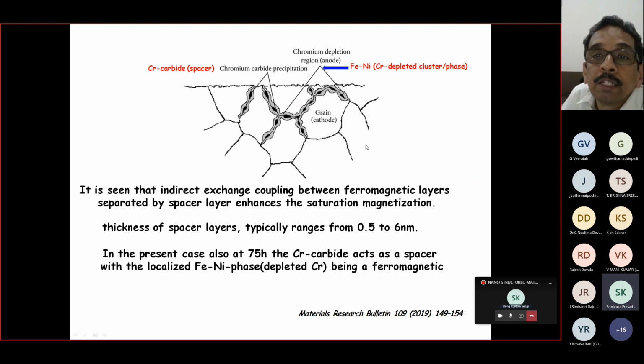And why this anomalous behavior? We try to explain it by saying that this is the chromium carbide precipitation, which I put in the dark region, and this is the iron nickel phase. Basically, what is happening is at 75 hours, the chromium carbide acts as a spacer, with the localized iron nickel phase acting as a ferromagnet. These two areas are being shielded because of this chromium carbide, which is not ferromagnetic.